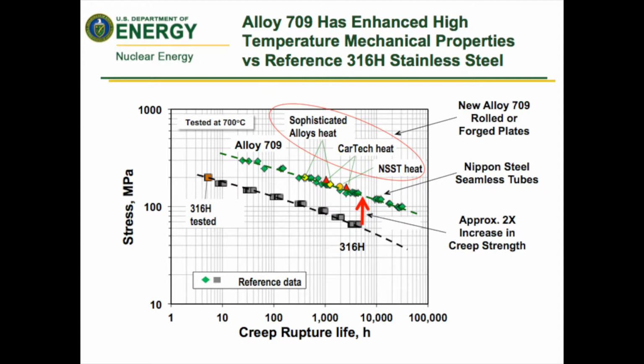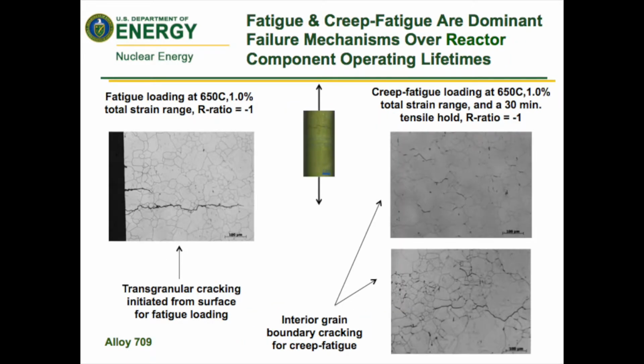You can see here multiple heats that we've already tested, looking at creep strength versus time, and you can see it is about a factor of 2 better than 316, which is currently in the code. So we're focusing on this as one of 2 materials. We also have a ferritic martensitic material, but that doesn't enter into the NEIP, so I'm not going to go into that today. There are some things that are particularly important for this class of materials.